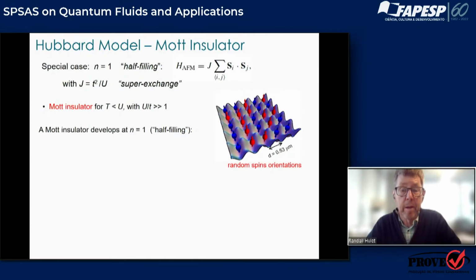It's an insulator because there's a gap, called the Mott gap, in energy that occurs exactly at half filling. And the chemical potential lives inside that Mott gap, and there are no excitations. So what gets created like this remains like that. Atoms, or electrons in an electronic material, don't flow. There's no transport because everything is stuck in place due to these high on-site repulsive interactions that inhibit the tunneling.